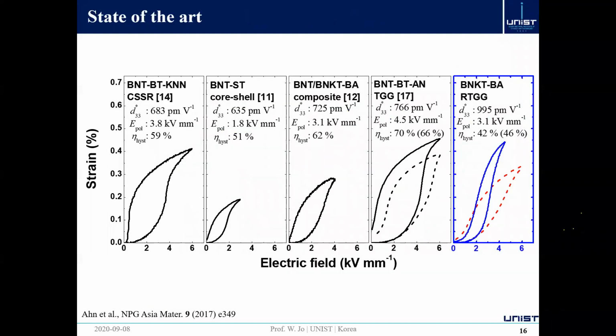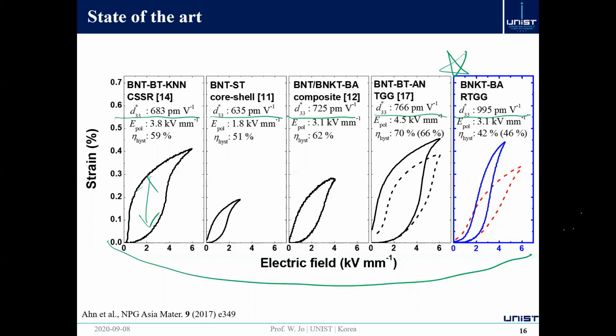Okay, so it seems that time is really flying, so let me speed up a little bit. This is the current state of the art of the largest strains achieved in lead-free piezoceramics at the moment. As you can see, even though we have a large hysteresis existing here, this Smax/Emax value is a lot above the normally achieved d33 values. But something I want to point out here is our recent achievement: Smax/Emax near 1,000 picometer per volt, which already fits real practical high-end applications. So I'm going to briefly talk about how we achieved this.